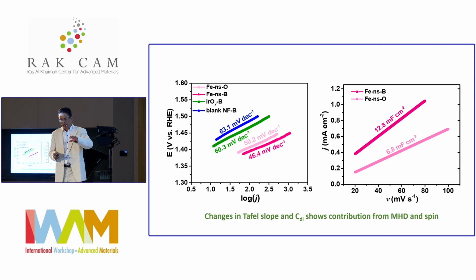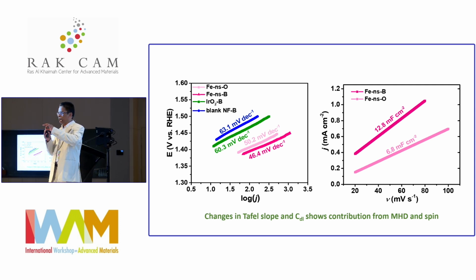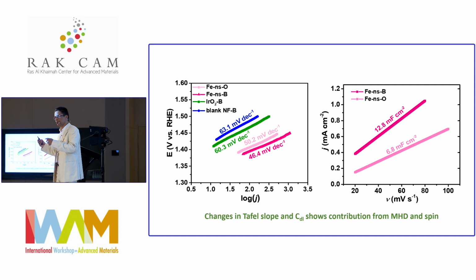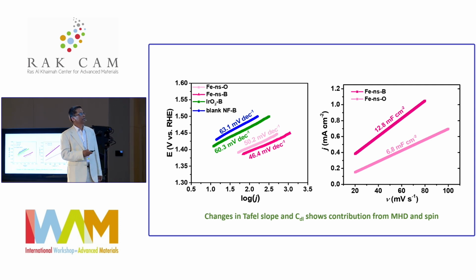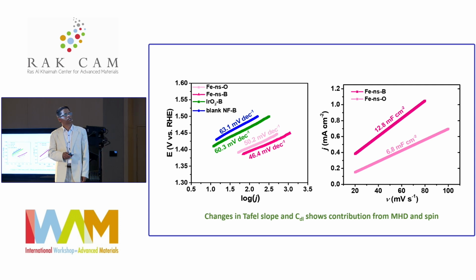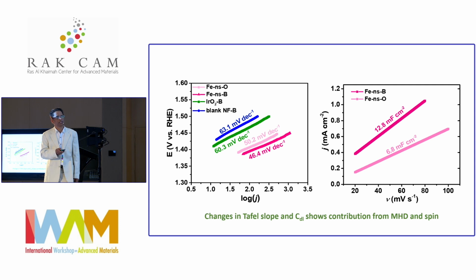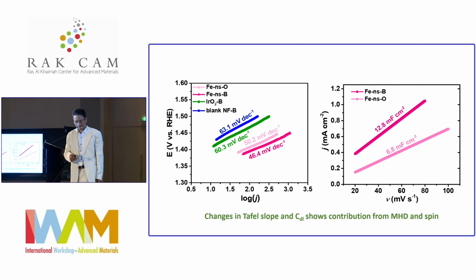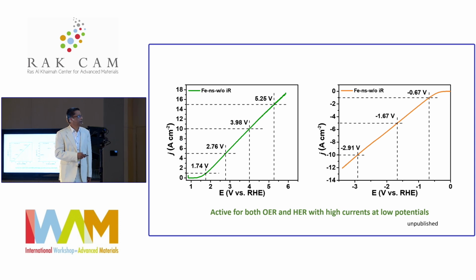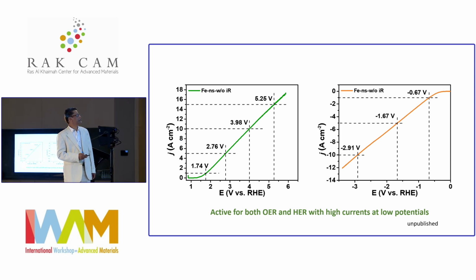So you make the iron structure on nickel foam and apply the magnetic field for a few cycles, and then you remove the magnetic field, and it still shows very high enhanced activity with a very low Tafel slope. The double layer ECSA also shows almost a 100% increase in active surface area. You can reach 1 ampere at 1.7 volt, and at 2.76 volt you get 5 ampere current, and at a higher level you can reach up to 15 ampere.